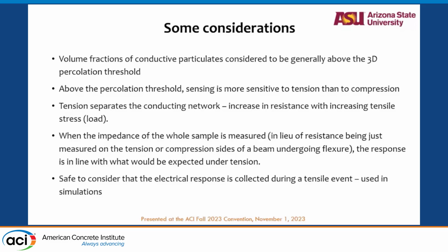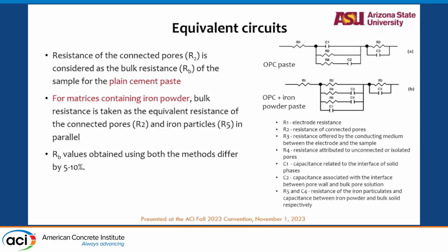So with the percolation threshold reached, let's say the specimen goes through tension. The conductive material, the iron powder, will separate apart from each other, resulting in a change in resistance. When we put flexural stress on the beam, the measurement that we get from the impedance spectroscope, we are assuming it to be tension, and it's a safe assumption because the compression side will have a resistance different from the tension, and tension will be the one that we observe in the results. Based on this, we also developed an electric equivalent circuit that we use for understanding the response. This will come back later again.